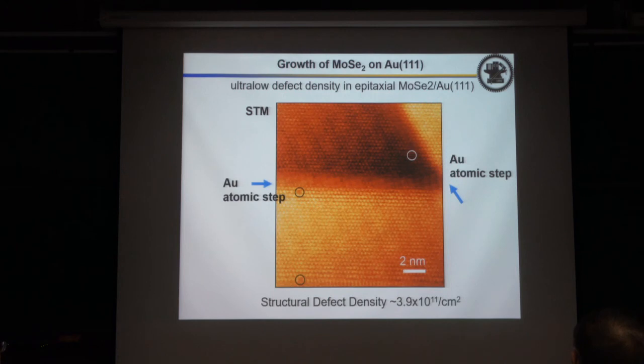The other problem is for this wafer-scale single crystalline film: do you see any domain boundary, like the FCC type, the kind of stacking? You mean the metal or the film? The film, for nitride or these TMDs. Actually, no, we didn't find any. We cannot find a domain boundary by STM. Naturally, you cannot expect all the nuclei to have perfect registry. Somehow, when they meet, they maintain a good registry and then relax the strain profile on the long range scale. That's probably consistent with this variation of the moiré pattern.